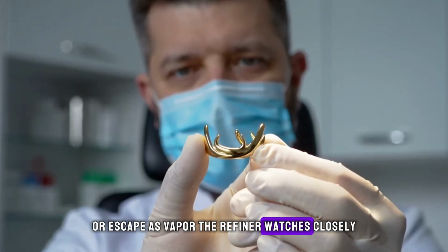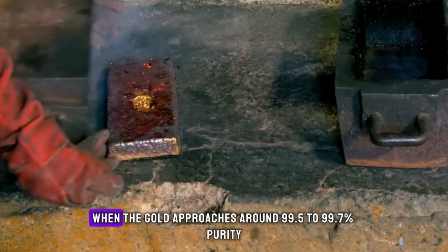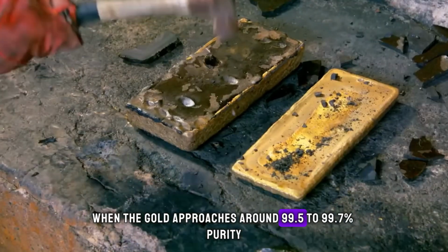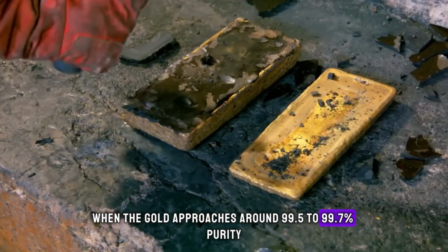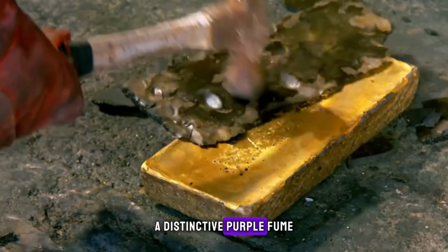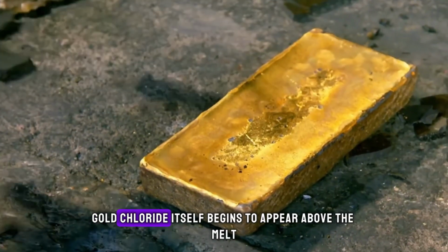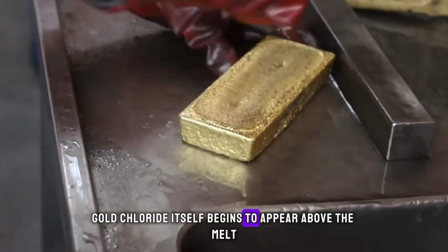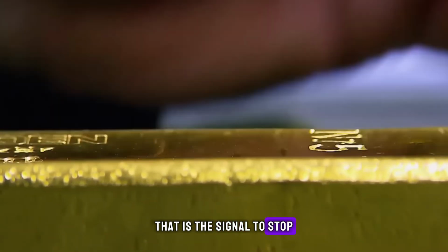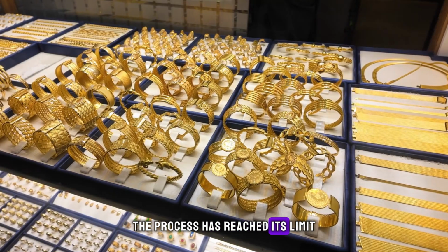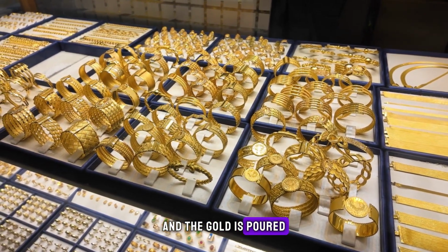The refiner watches closely. When the gold approaches around 99.5 to 99.7% purity, a distinctive purple fume, gold chloride itself, begins to appear above the melt. That is the signal to stop. The process has reached its limit and the gold is poured.